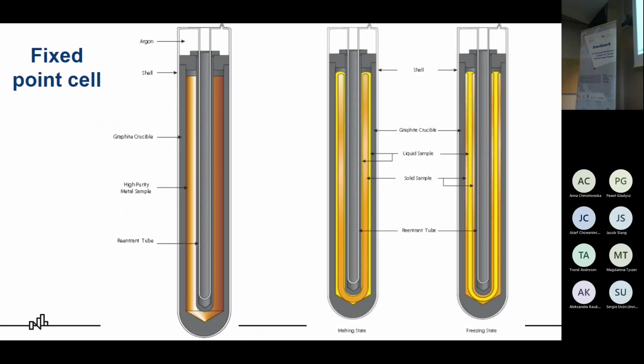We use the fixed point cell with high purity metal sample. And what does high purity mean? It is the rule of 6 nines, which is the purity of the metal is 99.9999%. So it is a really pure metal sample. The fixed point cell is submerged in hot oil, and when the liquid sample changes to solid sample, we have the freezing. So we want to measure the temperature at stable freezing state.